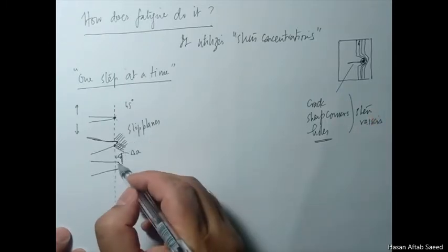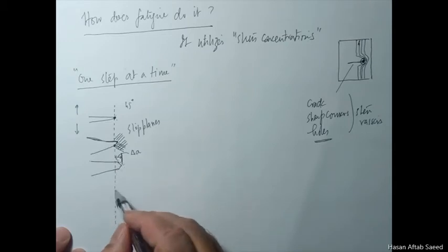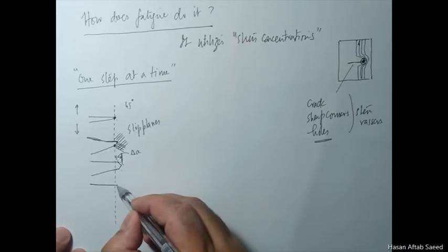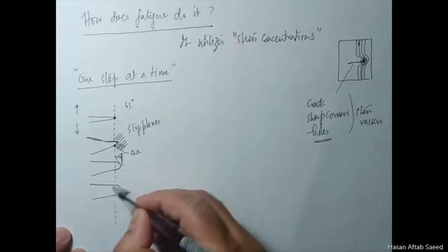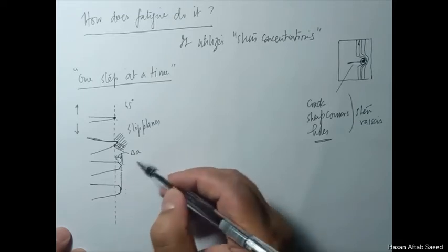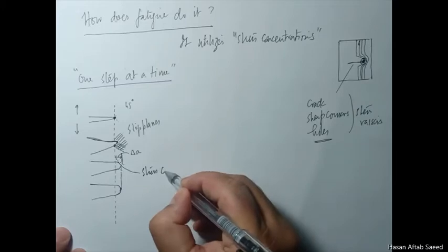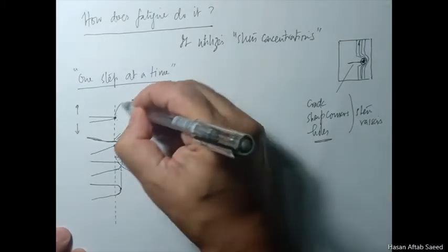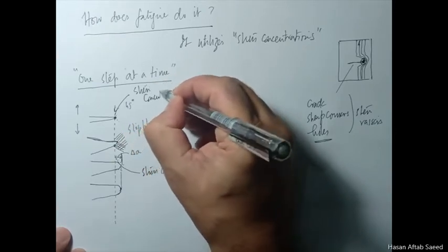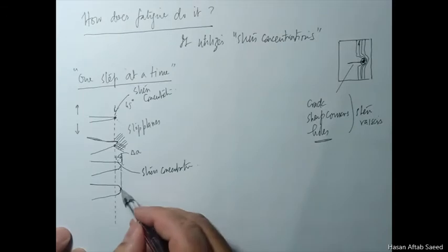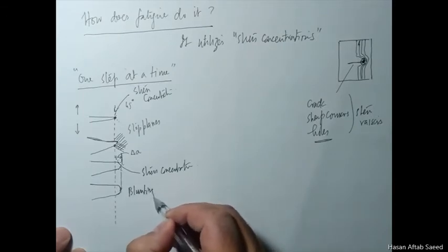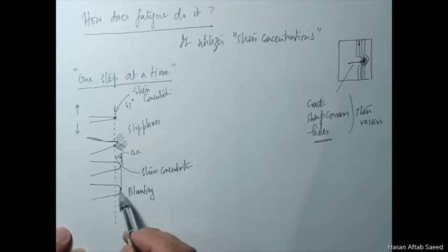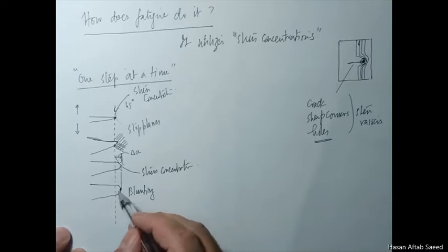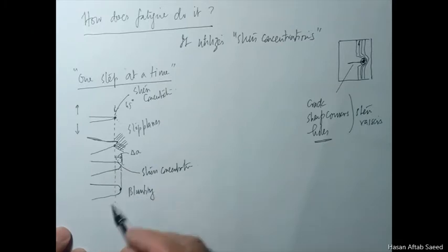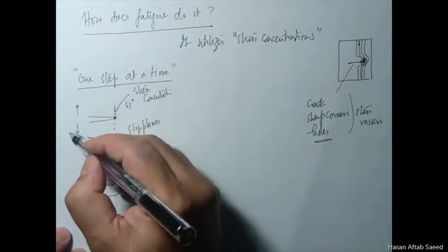Now, because this area is very highly stressed, plastic deformation takes place here, and a blunting of the crack tip occurs. There's the same point here. There was stress concentration here, as was here, very high stresses. But here, because the blunting occurs, there's no stress concentration anymore, because stress concentration is where you have a sharp corner. So after blunting, this is the situation. There's no extension anymore.